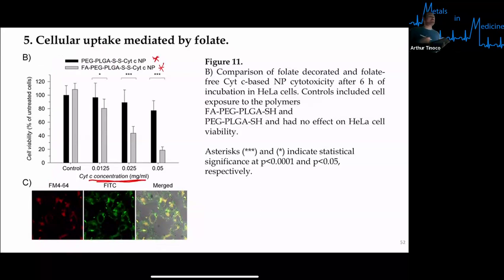And so we're treating them in a cell line that has a folate receptor. The idea was that you want to take advantage of that receptor to see if there's any selectivity. And what's observed is that you have a much lower cell viability in the presence of the nanoformulated cytochrome C when folic acid is available. You can see this dose response, and you get to the level of about 20% viable at the highest concentration of the cytochrome C. You do get somewhat of a dose response without the folic acid, but it's much less. So you get about 80% at the highest concentration. This is indicative of the folic acid possibly enabling a higher uptake. And possibly that higher uptake is the reason why you have a lower cell viability there.